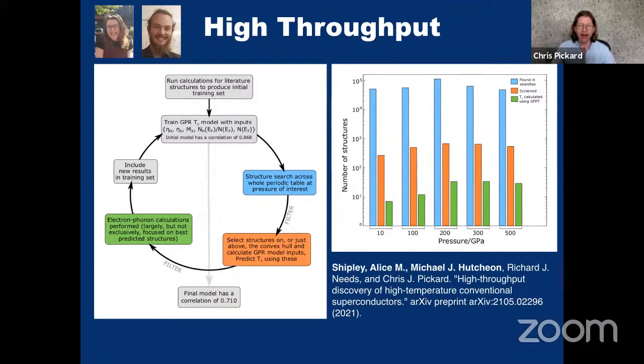to speed things up. The other advantage of this is that it allowed us to find structures that might not actually be dynamically stable in static lattice DFT, but might be stabilized by thermal effects or quantum zero point effects. So if you did a DFT calculation, there might be some distortion and it goes to low symmetry and it doesn't appear to be a superconductor. But actually, when you take into account the dynamical effects, it would symmetrize, it heats up and symmetrizes and might then be a superconductor.